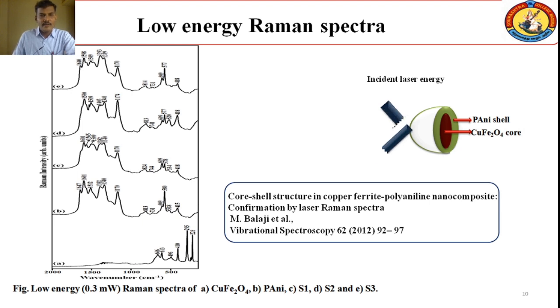Here you can see the low energy Raman spectra of the copper ferrite, polyaniline and 3 different composites S1, S2 and S3. In copper ferrite you can see a characteristic behavior of copper and ferrite element, and in the polyaniline you can see a characteristic behavior starting from 1647 centimeter minus 1 to 415. There is no resemblance because this is pure polyaniline, so there is no characteristic behavior of ferrite.